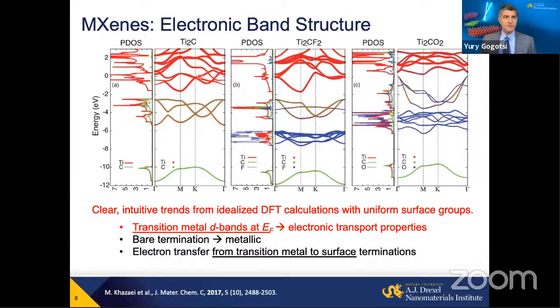And this is an example of calculated density of states. For example, for one of the simplest and actually one of the first discovered, titanium 2C MXene, you can see that there is a high density of states at the Fermi level when there is no termination. But typically, we get MXene with surface termination: oxygen, fluorine, OH. And you see fluorine termination significantly affects the density of states, and oxygen termination can also potentially open a band gap.